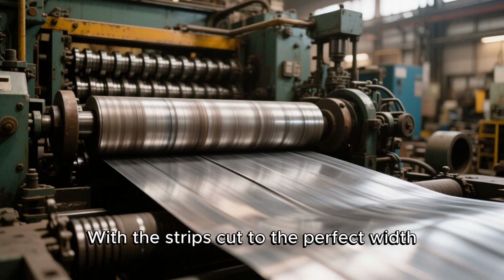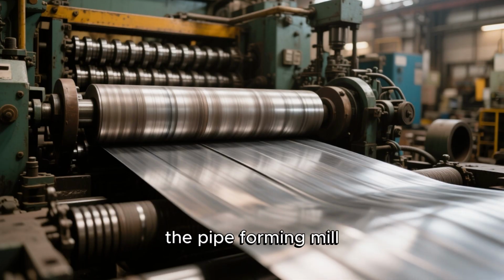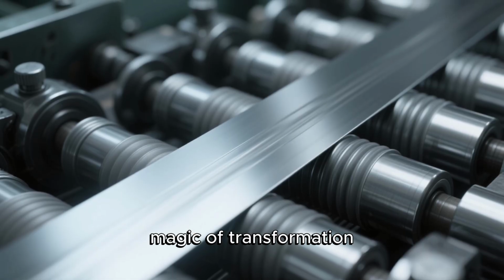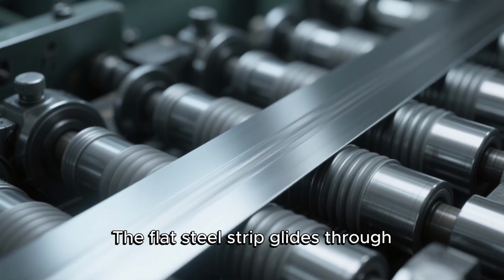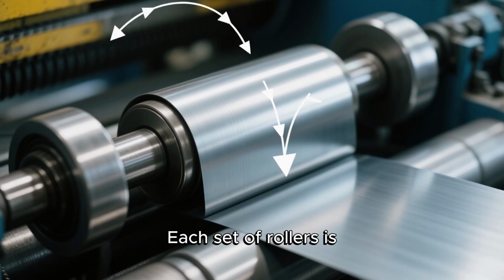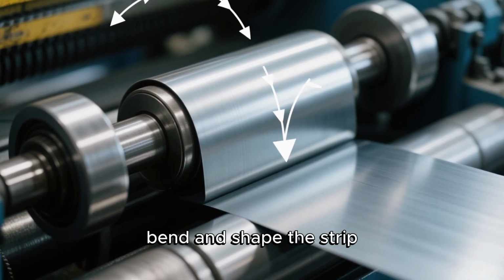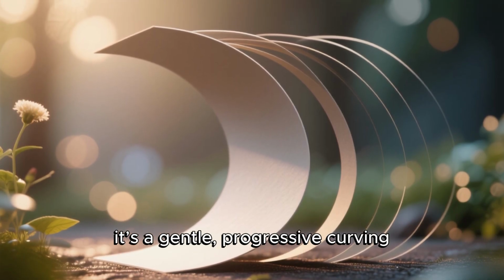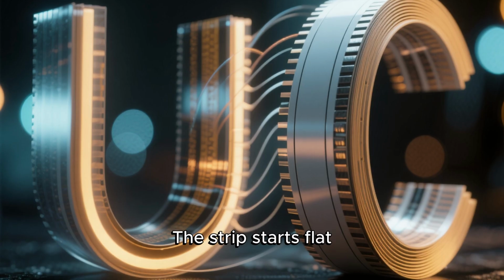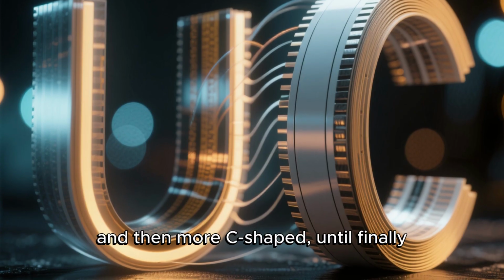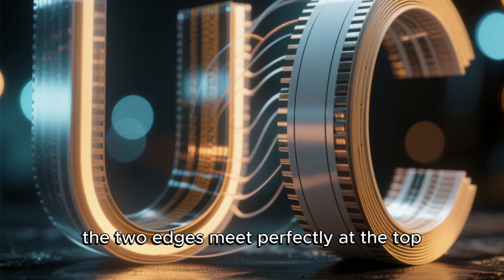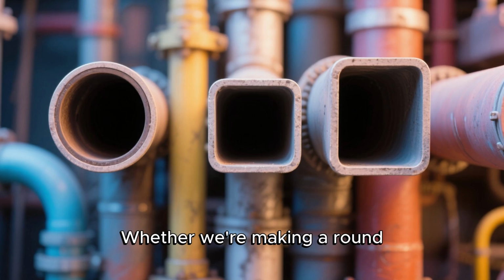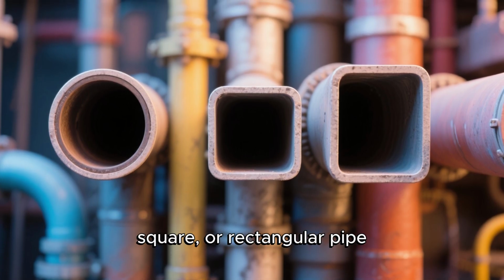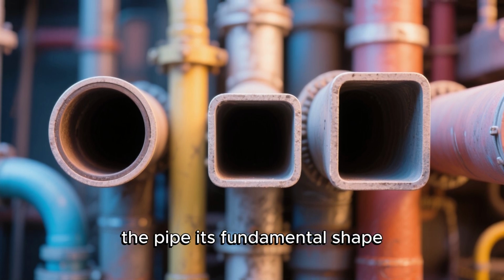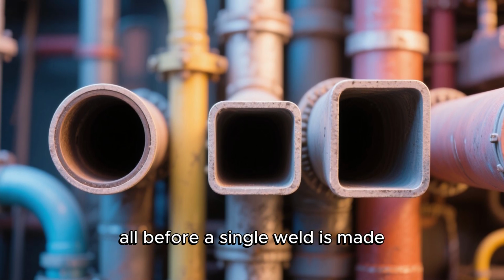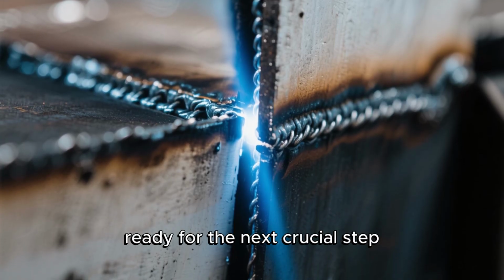With the strips cut to the perfect width, they now enter the heart of the factory, the pipe-forming mill. This is where the magic of transformation truly begins. The flat steel strip glides through a long series of rollers. Each set of rollers is meticulously angled to gradually bend and shape the strip. It's not a one-step process. It's a gentle, progressive curving. The strip starts flat, then becomes slightly U-shaped, and then more C-shaped, until finally, the two edges meet perfectly at the top, forming a hollow tube. Whether we're making a round, square, or rectangular pipe, this forming stage is what gives the pipe its fundamental shape, all before a single weld is made. The seam is now perfectly aligned, ready for the next crucial step.